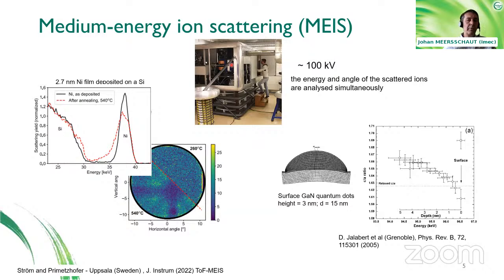Definitely, these ions will penetrate already a little bit into the material. This is what you can see here on the left. The helium particles are projected onto a sample of silicon, which is coated with 2.7 nanometer of nickel on the silicon substrate. After this sample is heated to 540 degrees Celsius, you see a distinctly different characteristic of the spectrum. I will explain the spectrum in more detail with regards to the higher energy, but you can already see that the spectrum is quite different from the spectrum that was obtained in its original state.